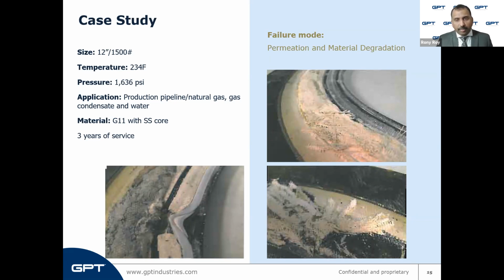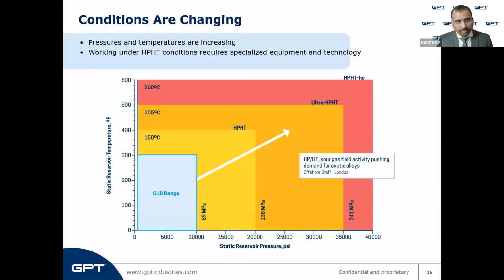matrix. This happened as the media in the line started to migrate and permeate through the gasket material made of GRE. Once the epoxy was gone, the gasket lost its strength, and the 1636 psi line pressure pushed the seal into the weakened glass structure and created a blowout.